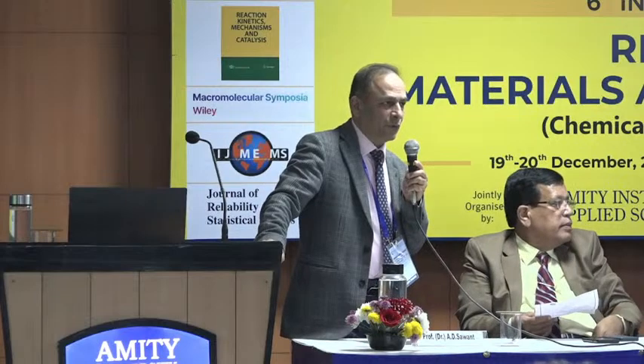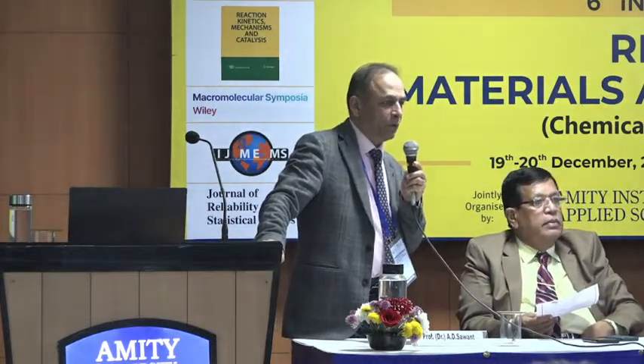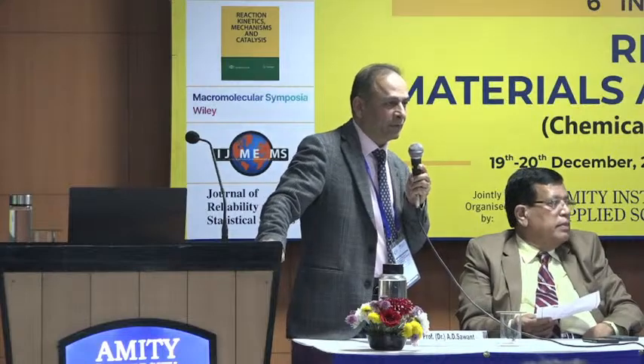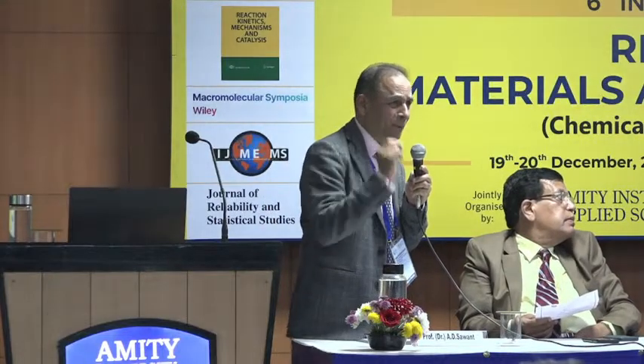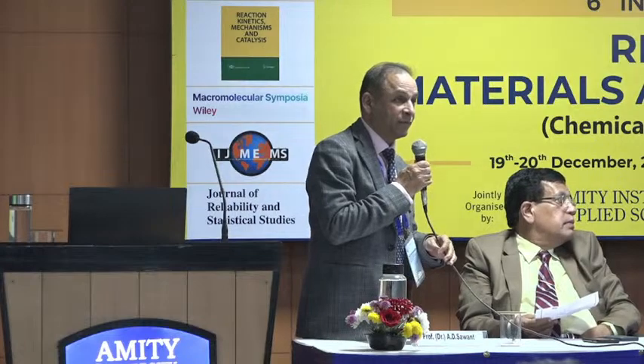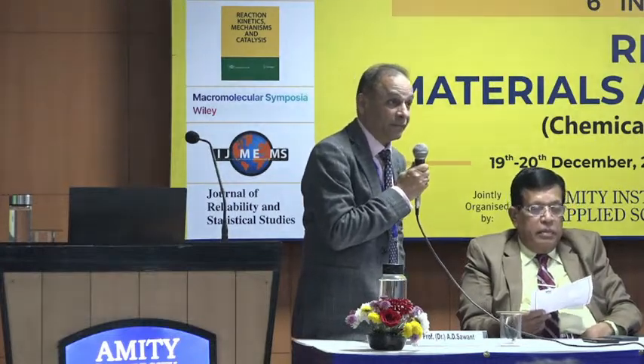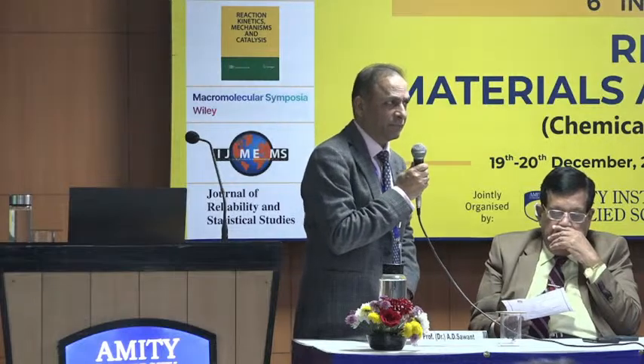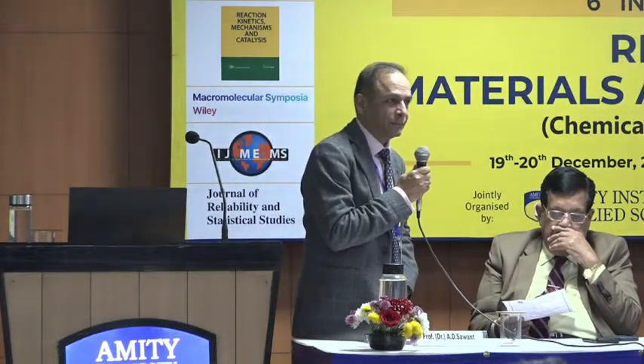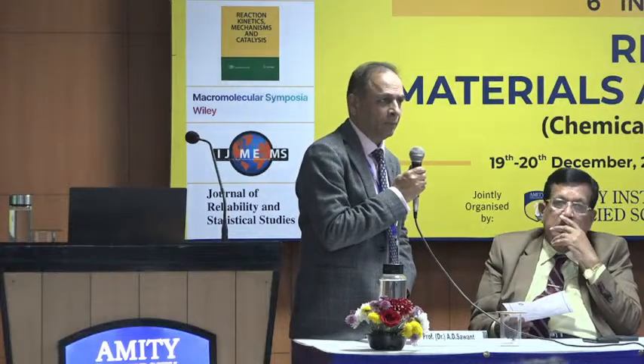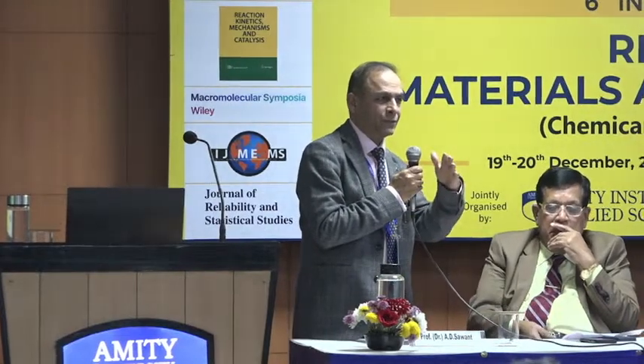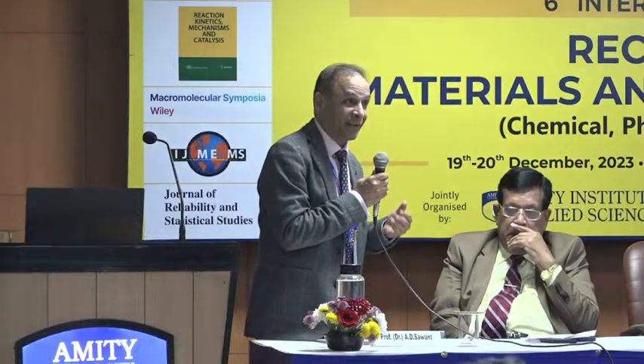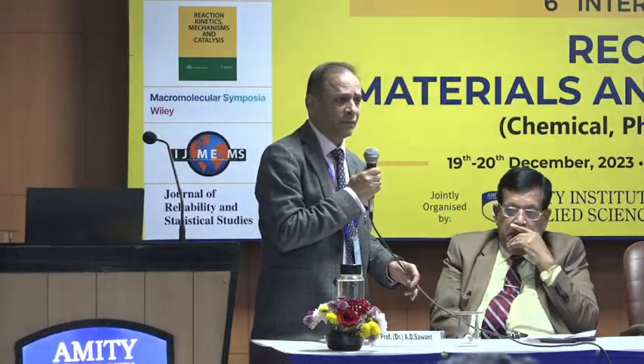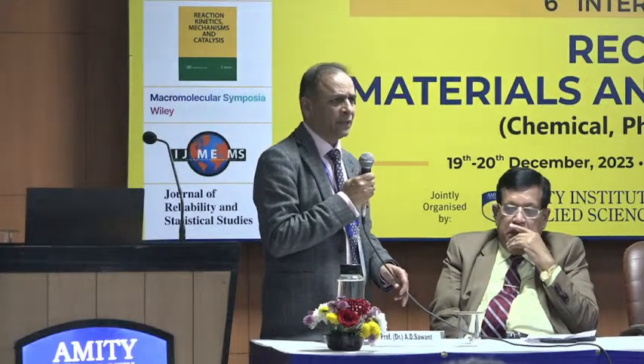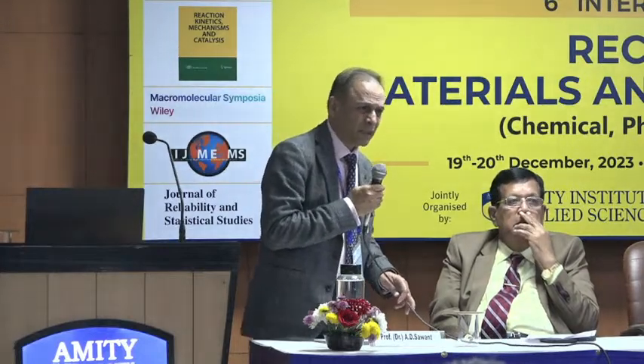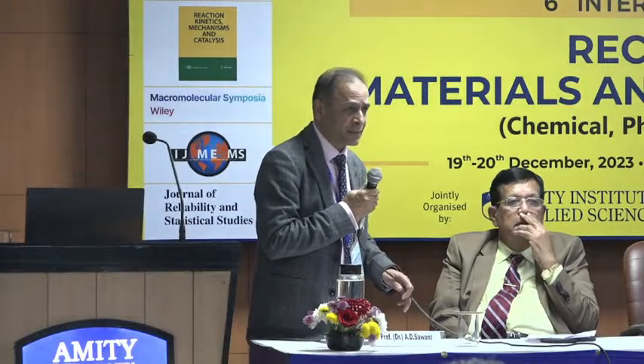Yes, I think lead is one of the problems. Although the claim made by Oxford PV is that they are using a very small amount, when you go to large manufacturing volumes, perhaps that may become significant. And leach tests have proven that lead comes out very easily. So that's an issue. But once we try to replace lead by, say, tin, which I'm also working on, we are finding that the efficiency level drops significantly. We are getting anywhere around 7 to 8%, sometimes 8%, and that's also with difficulty.